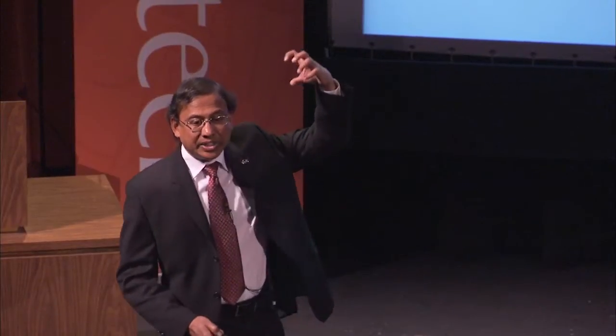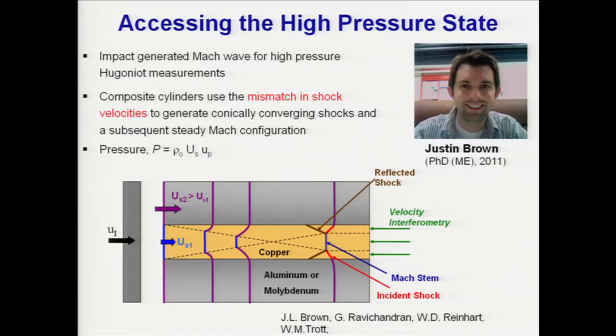Suppose we want to achieve pressures much higher than that in the lab. Justin Brown came up with this idea that you enclose the material of interest. In this case, we want to study the properties of copper. It is enclosed in a material where the shockwave speed is higher than that of the inner material. So when it's impacted, the wave is a plane shockwave. But as it propagates, the outer material, where the shockwave speed is higher than the inner material, moves ahead faster. But it cannot disassociate itself from the inner material because of continuity. So it creates converging shockwaves, which collide at the axis of the inner material.